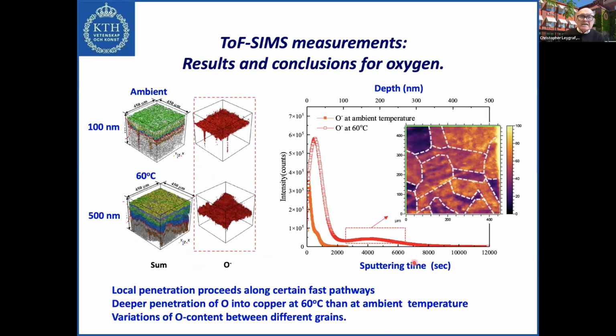The next slide here shows the first results. This is from results and conclusions for oxygen. You see here, this one is the ambient temperature result. It's a square here, 450 by 450 micrometer. And you see the result as a function of depth down to about 100 nanometers. And you can see that there are in certain areas here, very narrow areas, oxygen can even be seen deeper inside the material. At 60 degrees, the same exposure, you see that the ingress of these elements is bigger.